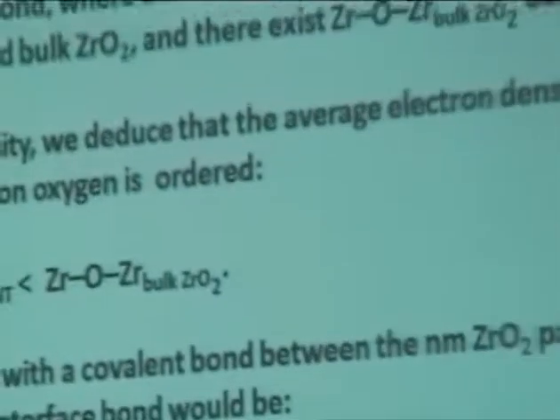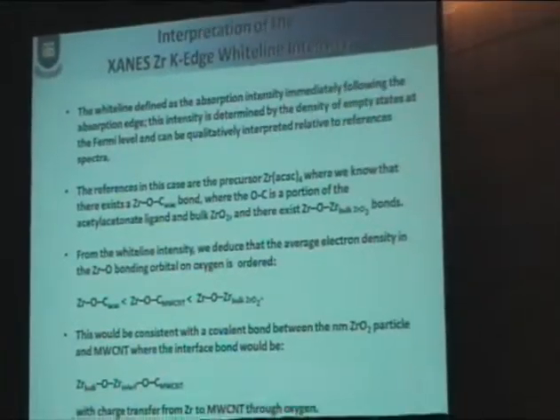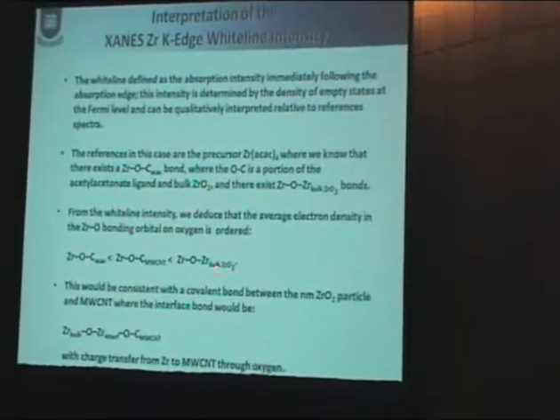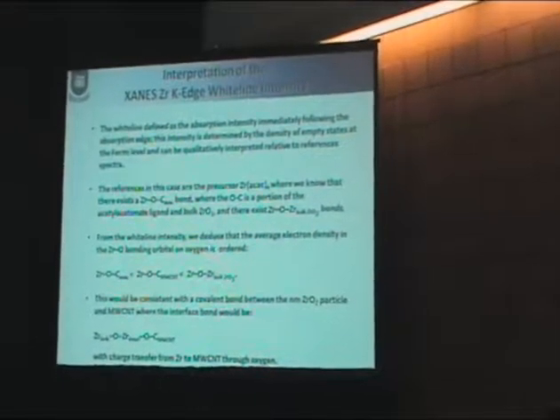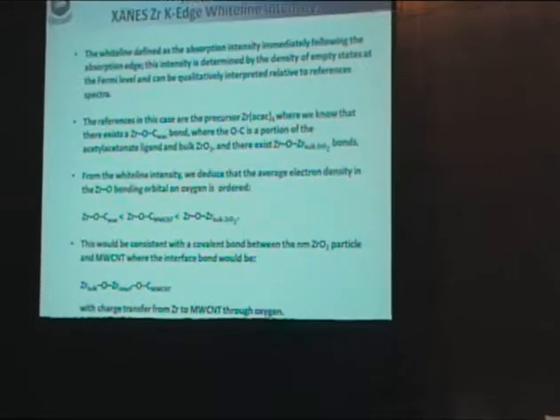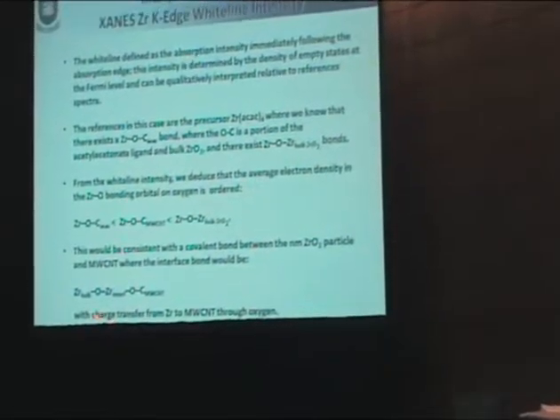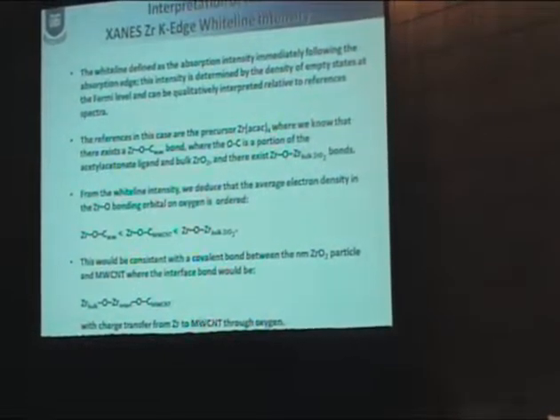And our catalyst falls right between the precursor and involves zirconium oxide. So all I can do is a qualitative discussion about which way electrons go. In this case, it's with respect to the bulk. With respect to the bulk, this would indicate that when we make small particles bonded to carbon, there's been electron transfer away from the zirconia. And so that's how we come to this charge transfer conclusion, with charge transfer from zirconia to the carbon nanotubes